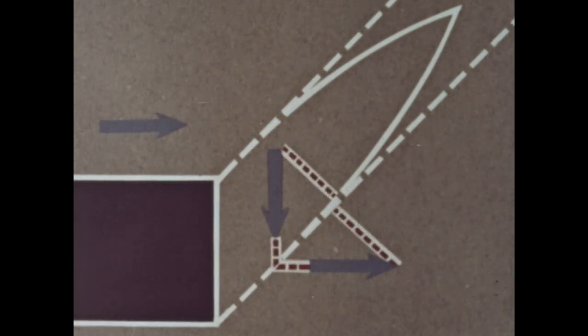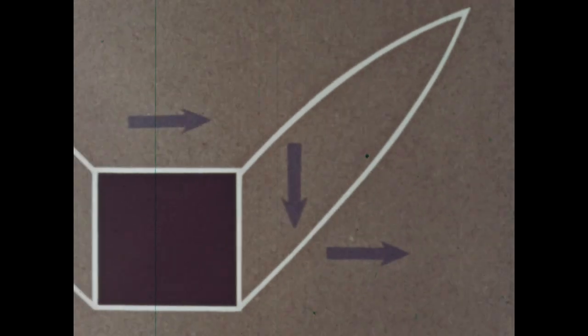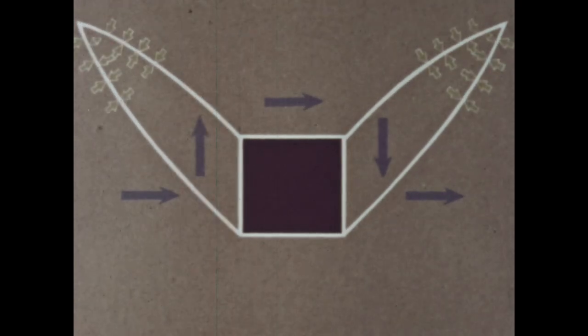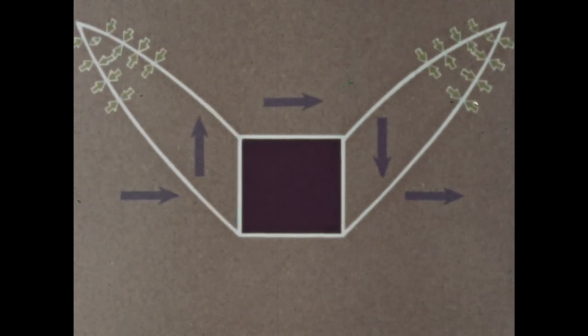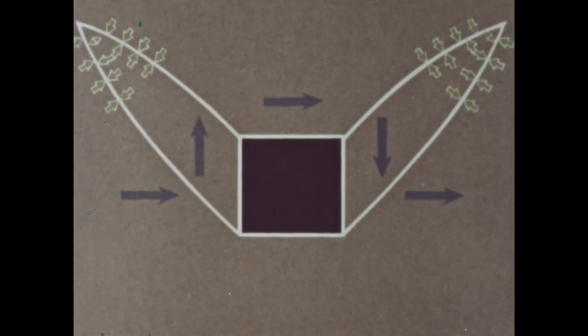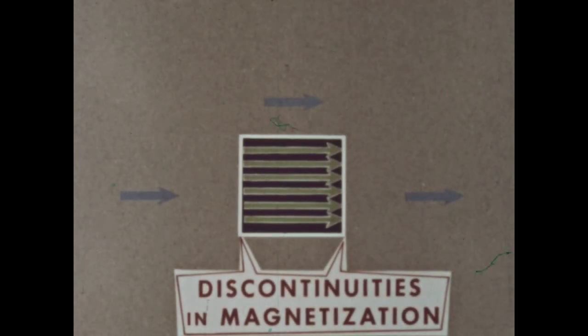Consequently, across the walls of a spike domain, the magnetization is nearly continuous. The H fields and resultant magnetostatic energy are therefore reduced to a minimum, although some fields remain around the tips. Thus, the sum of the magnetostatic and wall energies contributed by spike domains is less than the magnetostatic energy alone that would be present if spikes did not form.